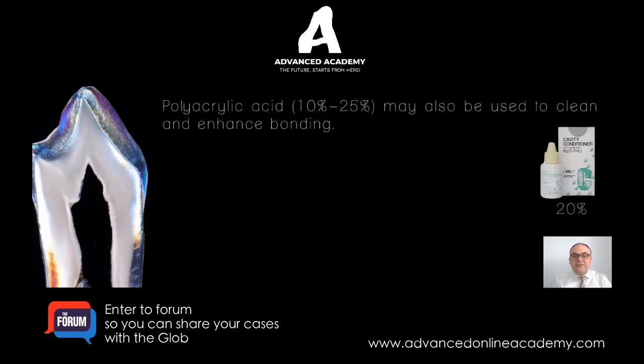If you have a glass ionomer material that you use, it comes with a polyacrylic acid, 20%. It's a very weak acid, optimum to just clean the surface. You just take it with a cotton pellet or a micro brush and scrub the surface with it. It's perfect for cleaning the surface.